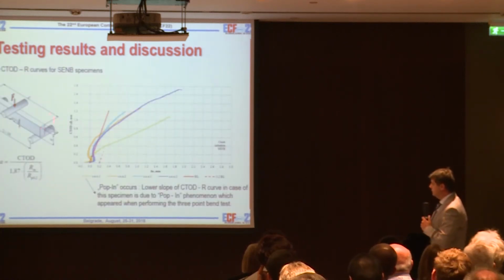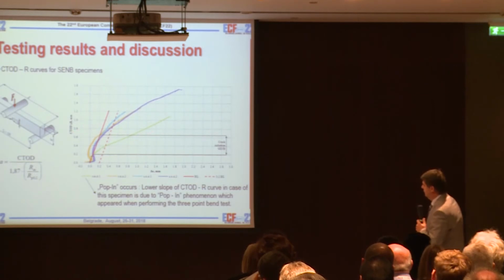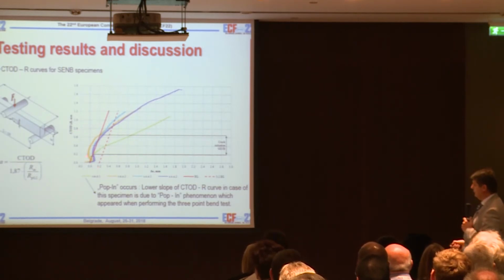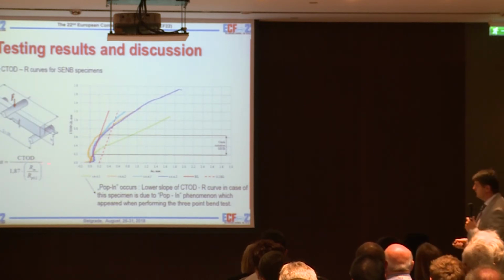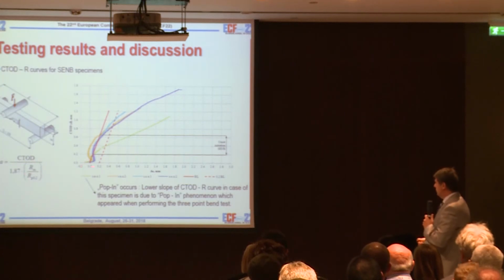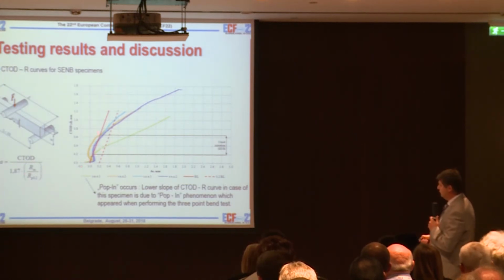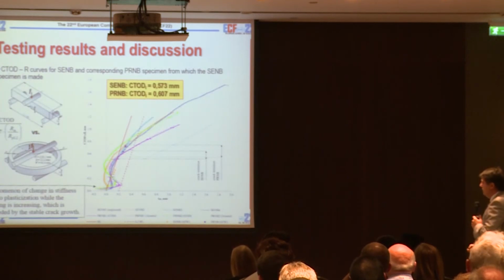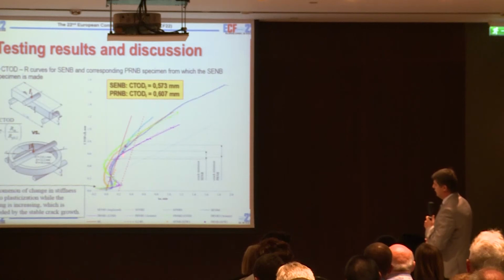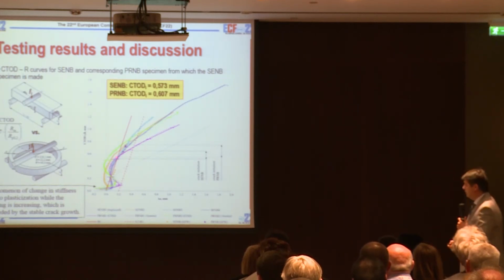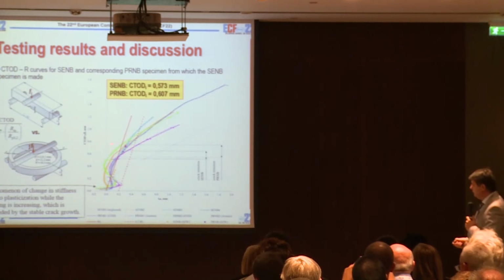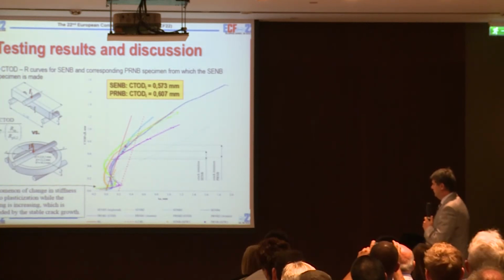So here we have the results of the CTOD R curves. Here are made by delta 5. This is the blunting line, and the formula used is in the standard procedure. So we have the crack initiation area from these different specimens, and also we did the same with the same blunting. And we have also crack initiation. So we can see the difference: here is the single edge notch bending, and here is the pipe specimen crack initiation. So it's almost the same range, even getting some higher values of CTOD.